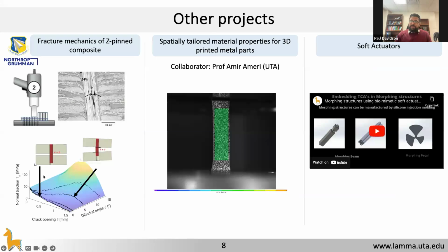Then there are other projects where we work with Northrop Grumman to look at Z-pinned reinforcement and how we can characterize the cohesive behavior for the interface with the Z-pins. Then I'm working with Dr. Amir, where we are looking at tailoring material properties for 3D printed metal parts, which we can use for novel ways of deflecting cracks, or making sure the cracks go the way you want them to go. So there's a video which shows that we can actually change the crack path.